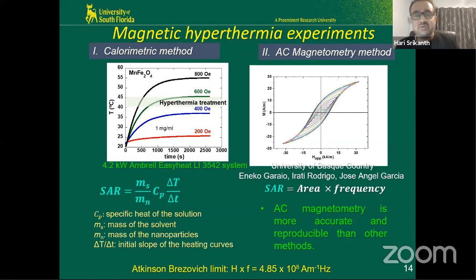And so this is what we need to keep in mind, that because this treatment has to be sustained for about 45 minutes to 1 hour, okay, this hyperthermia, for it to be effective, we need to make sure that the patient can withstand the conditions for that amount of time. And different people, of course, have different pain thresholds. Some of them can actually handle more pain than others. So this is not a fixed number, but it is a guideline for you to keep in mind that you cannot exceed some extreme values when it comes to these conditions. So we are very limited in terms of choice of the parameters that we can use to increase the SAR.